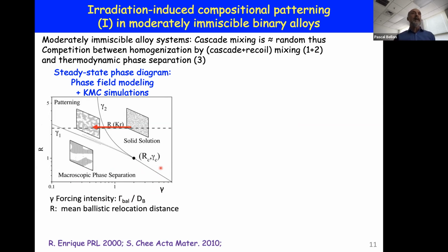What's intriguing, and it was not realized at the time when Raul Enrique did his PhD work here at Illinois, is that there is a critical length scale, RC, or relocation distance, above which a new steady state regime opens up, where material spontaneously would want to stabilize itself in a steady state that is nanostructured, as illustrated by these KMC simulations here.